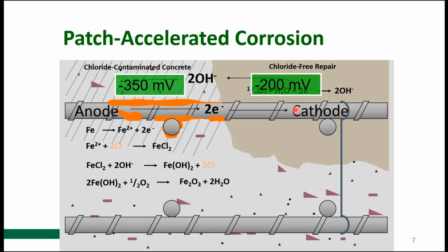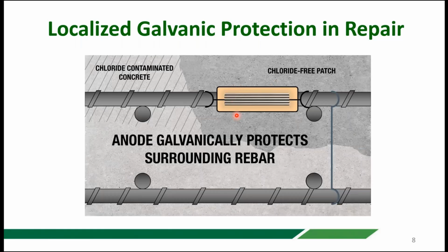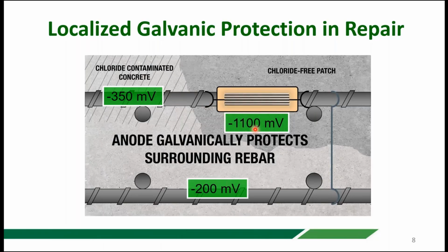We can address that mechanism locally by putting a galvanic anode into the repair. And even though we still have chloride-free repair and we may still have chloride-contaminated concrete surrounding, this will either slow down or completely stop the corrosion, because this anode will have a corrosion potential that's much more negative, something around minus 1100 or minus 1000 millivolts. And that's more negative than the steel in the chloride contaminated concrete or the steel in the repair itself. So current is going to flow from the anode to the steel, and the steel is not going to corrode as a result of that. And that's just because, again, you've got these voltage differences, and the most negative thing is what's going to corrode, and current's going to go from the more negative thing to areas that are less negative, as indicated here.